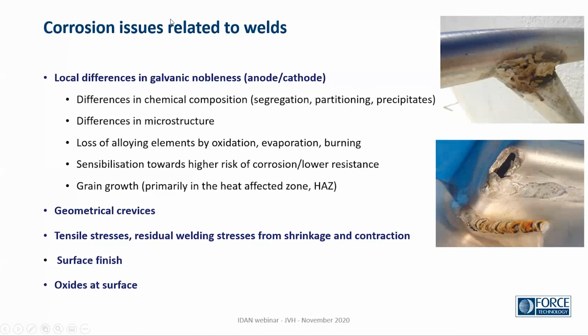But when we have welds, there might be several problems with this resistance from passive layers, and other problems too. If we have two materials with different galvanic nobleness, then we will have corrosion between the two. An example might be this part which has been in a pickling bath, an acid, where we can see that some parts were less noble and disappeared in the acid, and this one also to some extent.